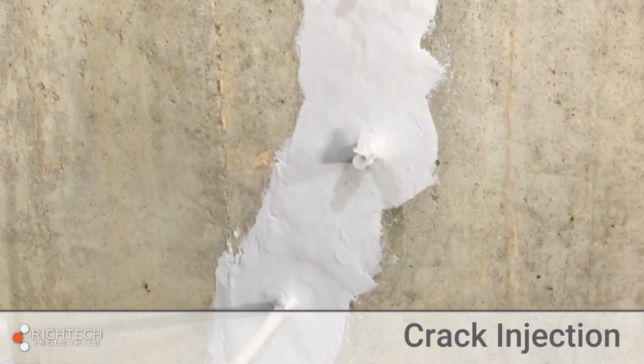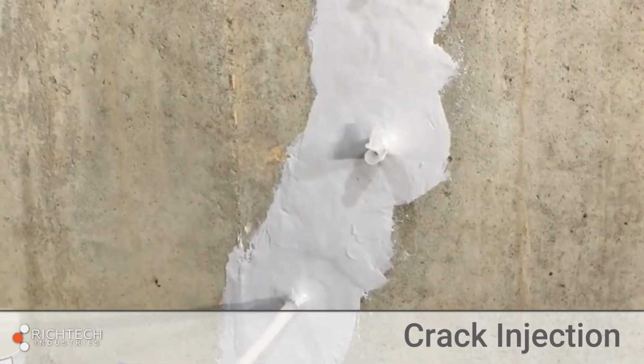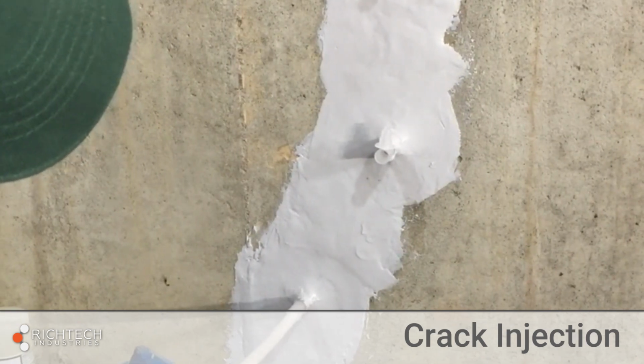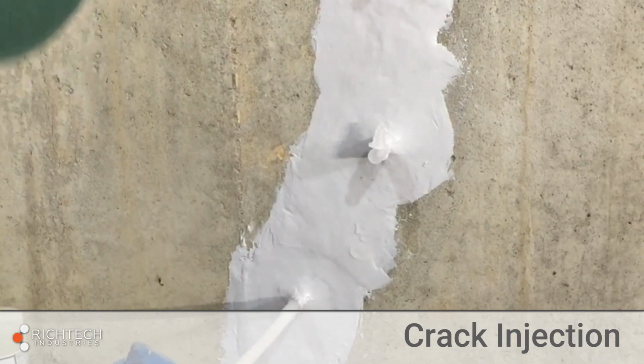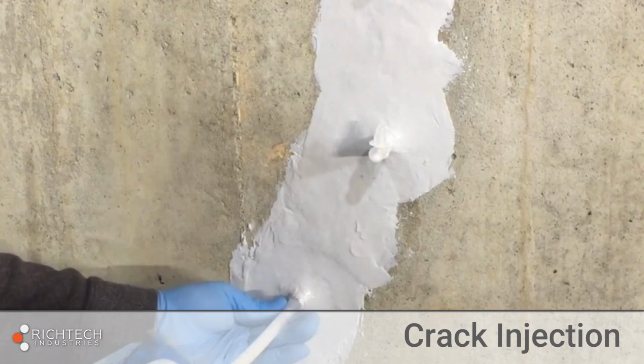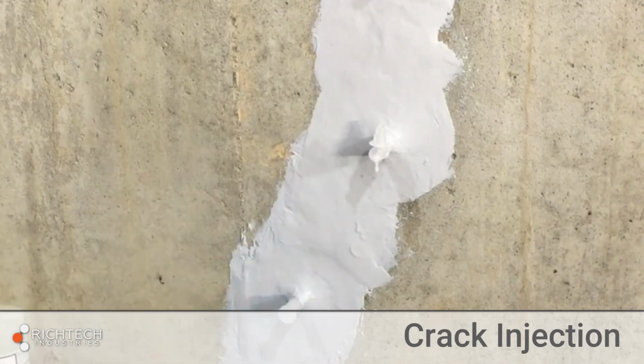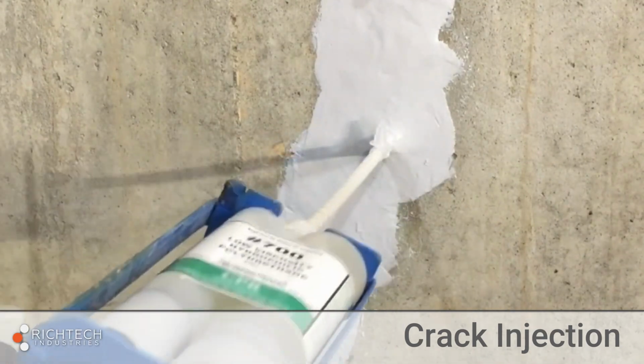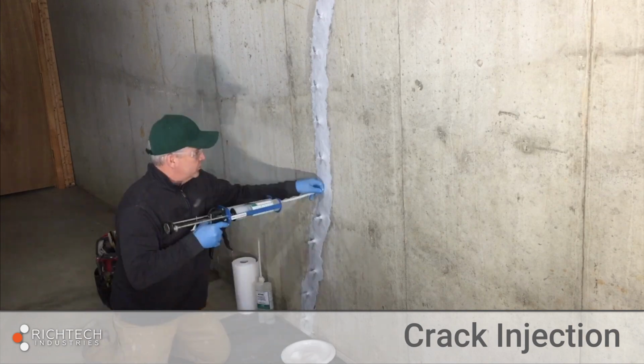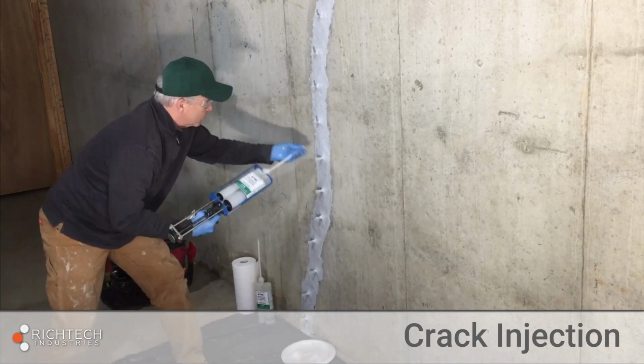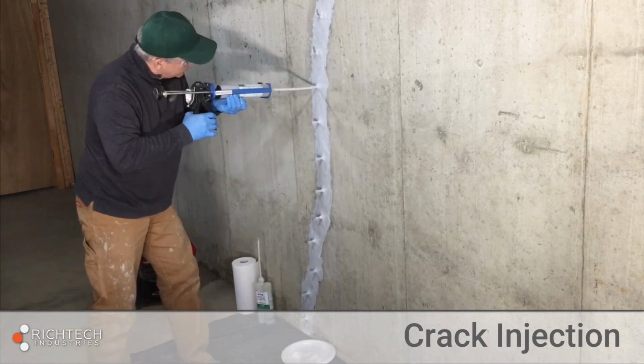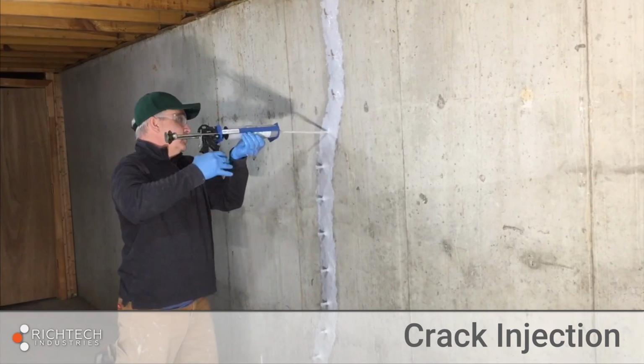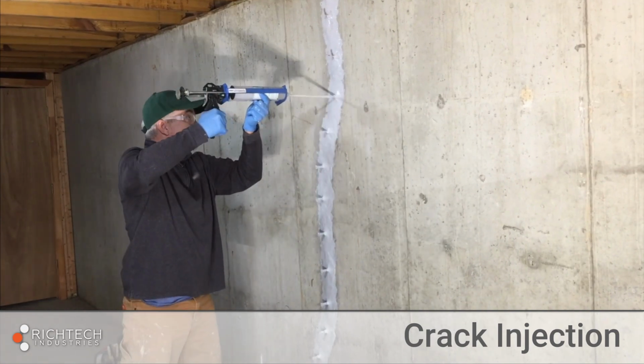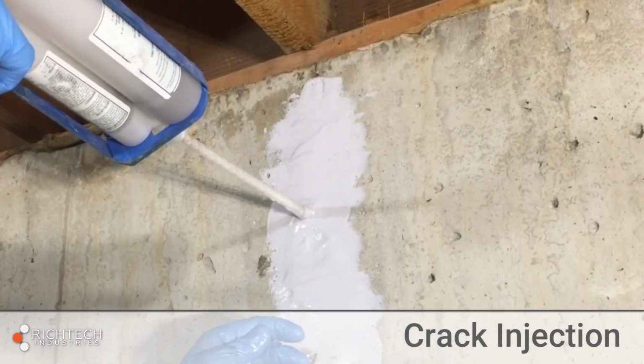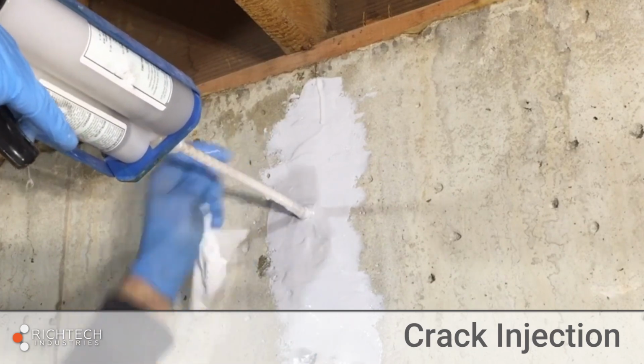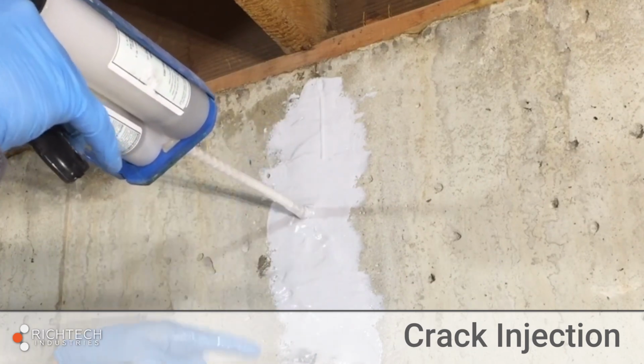Starting at the bottom, slowly and steadily inject the polyurethane until it begins to come out of the port above. Once it starts coming out, remove the gun from the port and cap it. Repeat the process all the way up the wall to the top port. When the resin comes out of the top of the sealed crack, it has been completely injected and is now ready to cure.